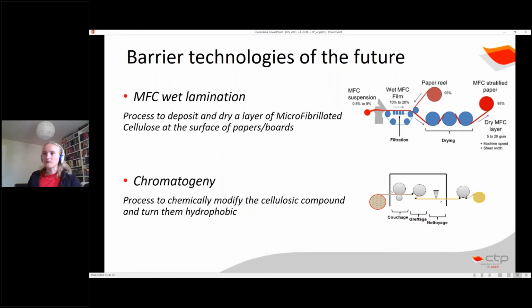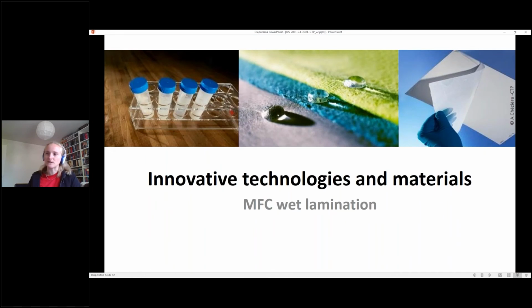At CTP in the recent years, we have worked on two specific barrier technologies that we hope are barrier technologies of the future, and that bring good barrier performances to paper and board substrates without adding plastic materials on top of it. The first one is called microfibrillated cellulose wet lamination. This technology is a process that deposits and dries a layer of MFC at the surface of paper and board. I will go a bit more into detail on the technologies right after. And the second technology is called chromatogeny. And this one is a process that chemically modifies the cellulosic compound, so the cellulose substrate, in order to turn it hydrophobic. But let's go into a bit more detail on MFC wet lamination first.